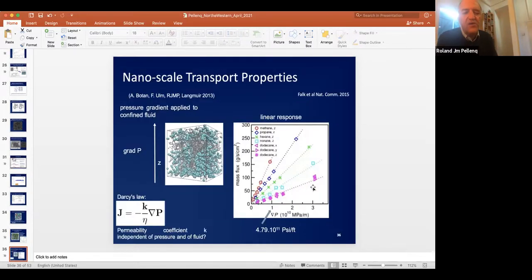So first thing we're going to do, we're going to use MD, molecular dynamics this time. It's pure MD, solving Newton's equations for those molecules in the pores with interactions. So we have interaction between the molecules, and interaction between the molecules and the carbon strands that make the matrix itself. And actually, we're going to apply an out-of-equilibrium condition. So we're going to give a force to the center of mass of every molecule to make them move in one direction, for instance, the Z direction. And that force will be divided by the surface of the box. That will be a pressure.